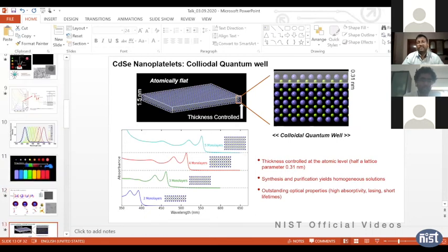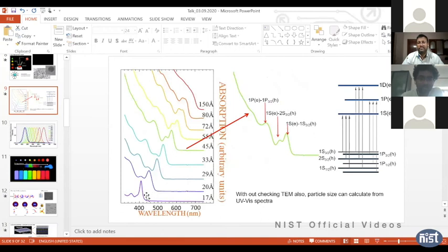Yeah, you can see from the UV-visible spectra the different sizes: 1.7 nanometer, 2 nanometer, 2.9 nanometer, and 15 nanometer, which is almost bulk. When your particle size is different, here you can see the distinct bands very nicely. If your sizes are mixed, like we have a mixture of particles, we cannot see this kind of difference.